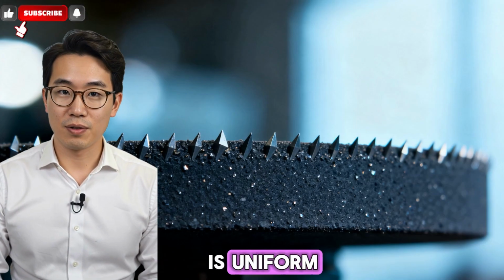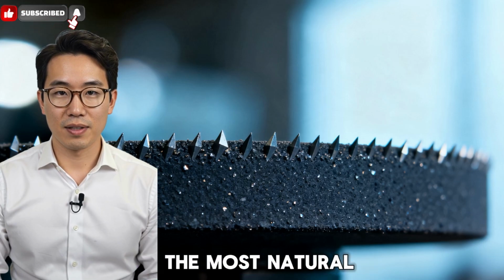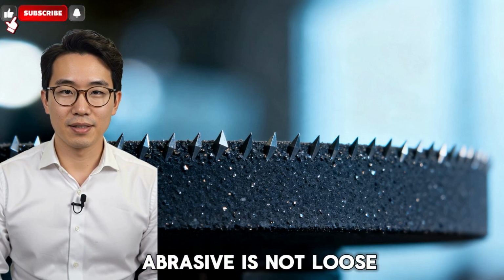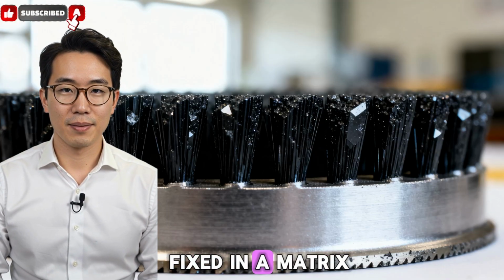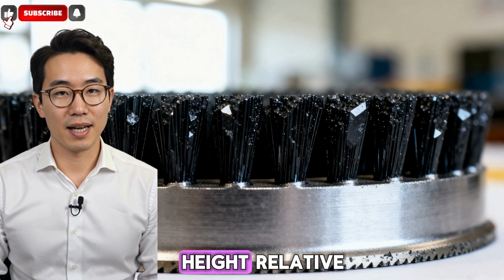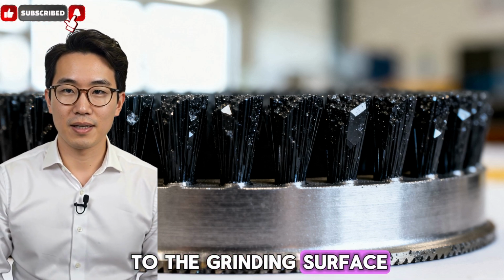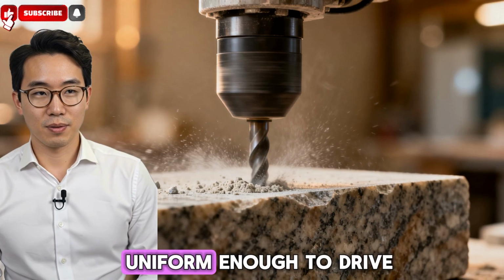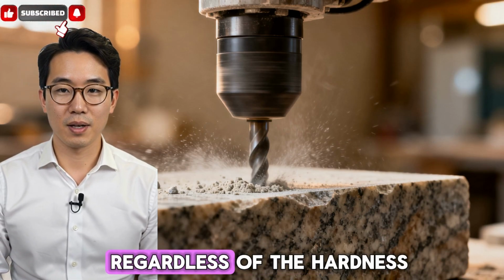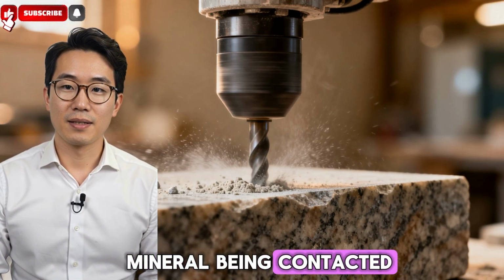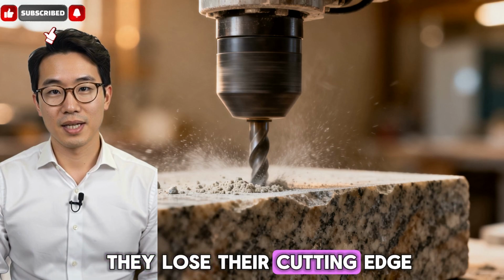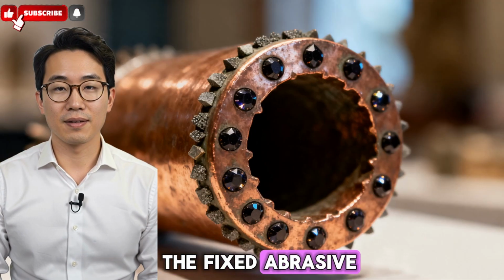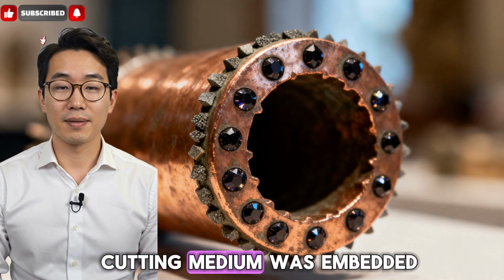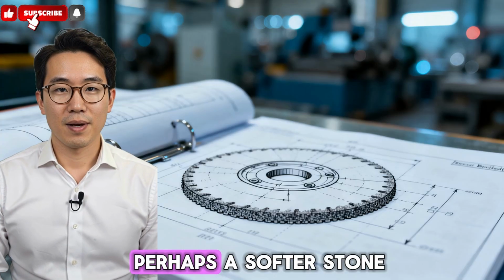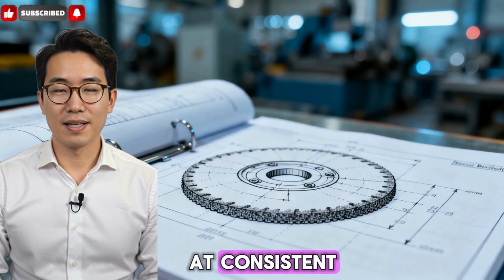If the groove depth is uniform across both minerals, the most natural explanation is that the abrasive is not loose, that it is either fixed in a matrix that holds each grain at a consistent height relative to the grinding surface, or that the contact pressure is high enough and uniform enough to drive all grains, regardless of the hardness of the mineral being contacted, to the same depth before they lose their cutting edge. The fixed abrasive hypothesis, the idea that the cutting medium was embedded in a matrix, perhaps a softer stone that held the grains at consistent heights,